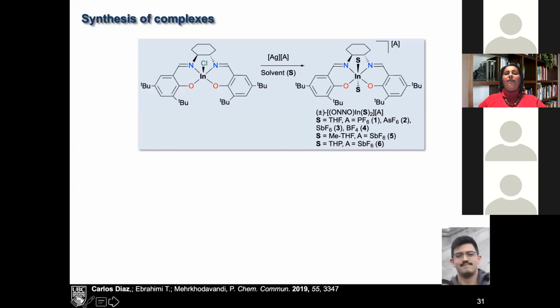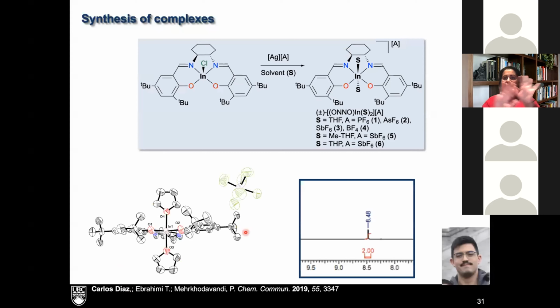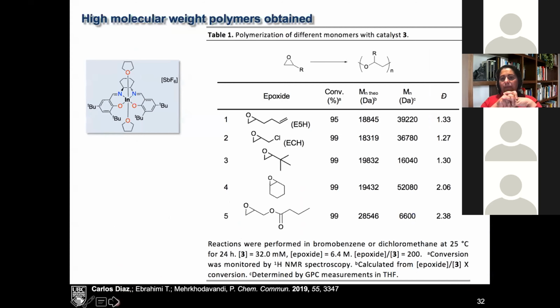So I have some more time, so I'm just going to talk about some work by my student Carlos really quickly. He was able to generate cationic indium complexes. The specific structure I wouldn't worry about too much, but they're cationic indium compounds that were able to polymerize epoxides. Here are a number of different epoxides. What's important is we're including epoxides that can be functionalized. It's really important because we can do post-polymer functionalization, as you'll see.